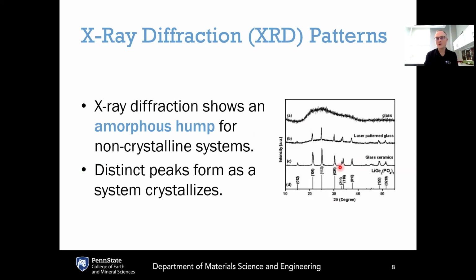How do we measure the structure of materials? The most commonly used method is X-ray diffraction. With X-ray diffraction, you are radiating the sample with X-rays, and then you can measure the diffraction pattern, and the diffraction pattern is going to show you if there's order in your structure, and the positions of the peaks and the intensities of the peaks would correspond to that structure of the material.